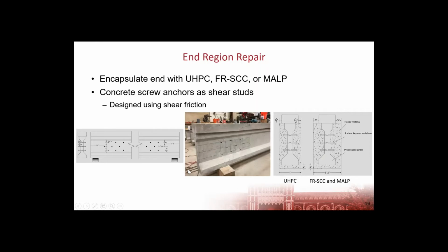We roughened the surface using a grinding wheel, basically trying to simulate what you could do in the field. And then we used concrete screw anchors as shear studs, which were basically Tapcon concrete screws. We designed a pattern for those shear studs that would span the entire repair area, but would be offset on either side, so we didn't have two screws at one point on the web.